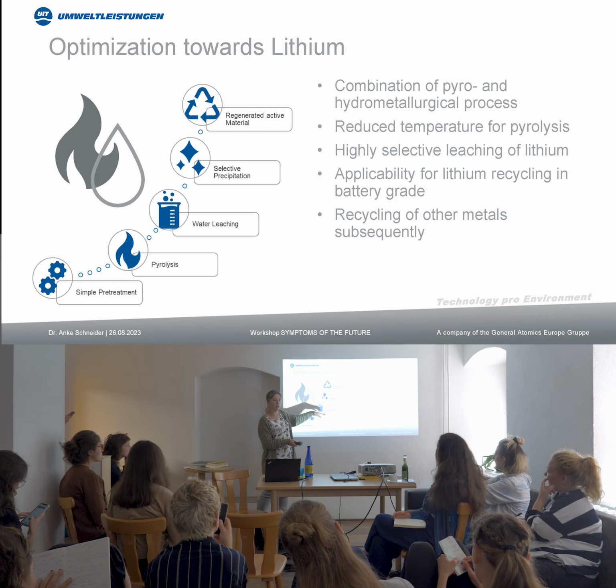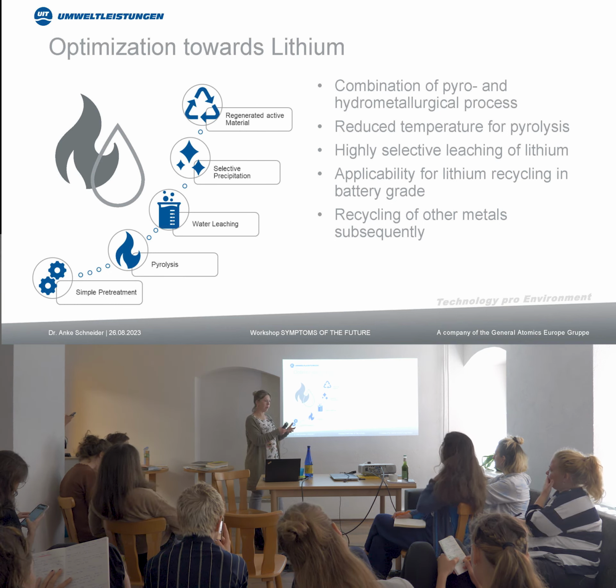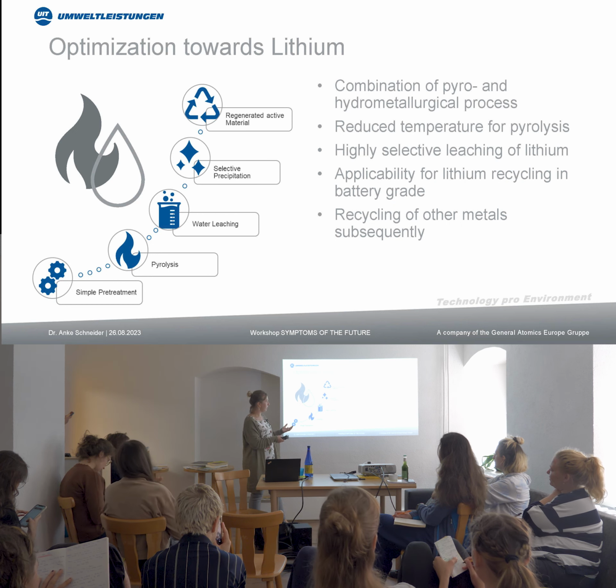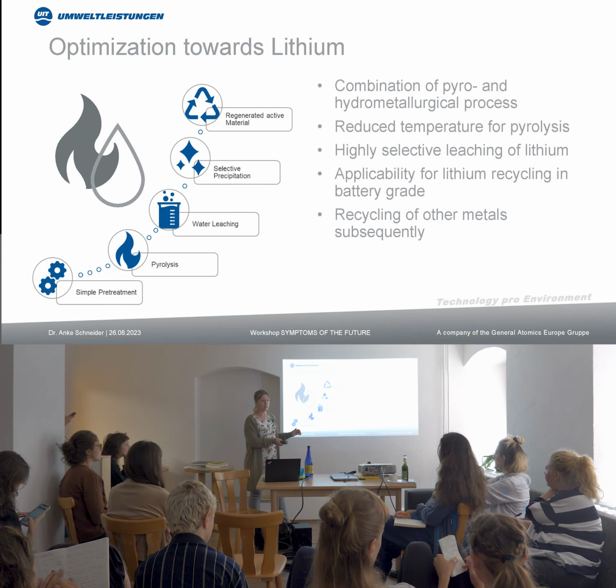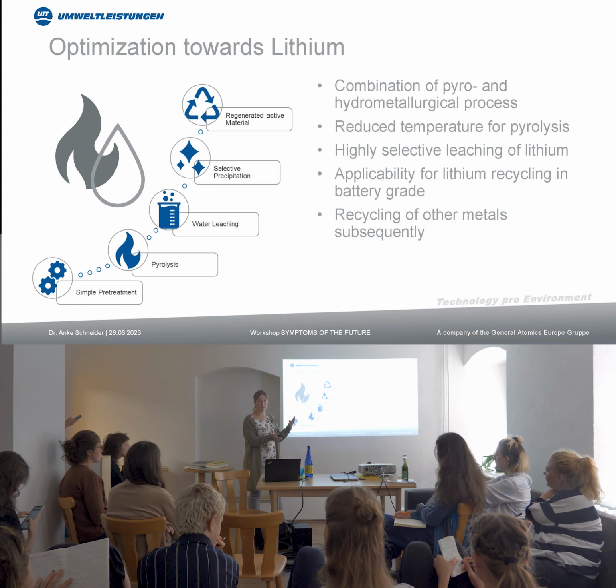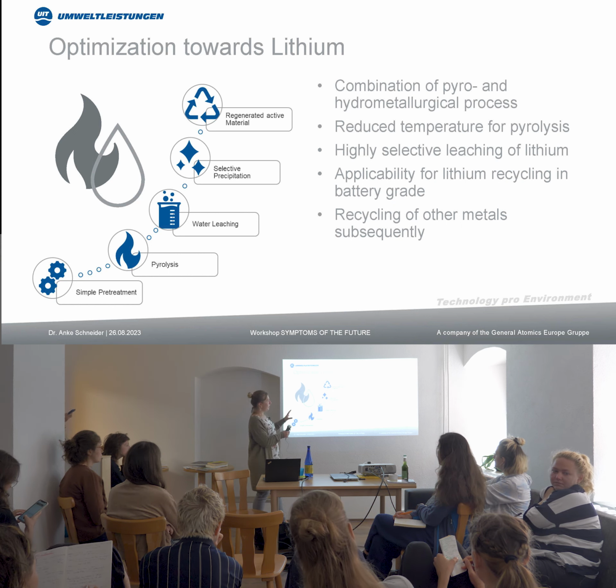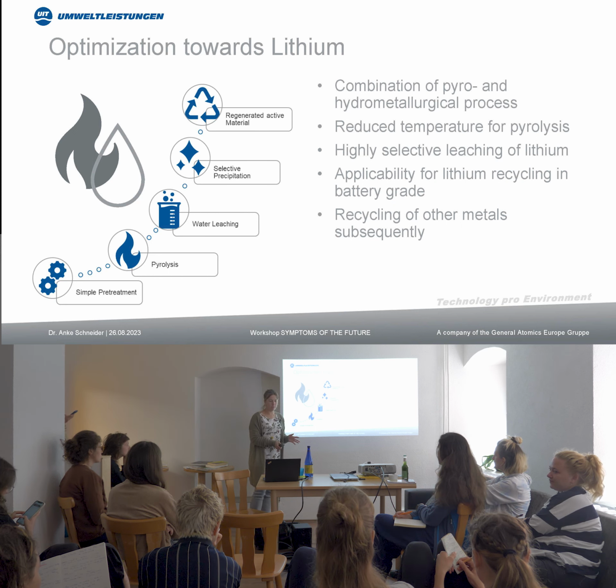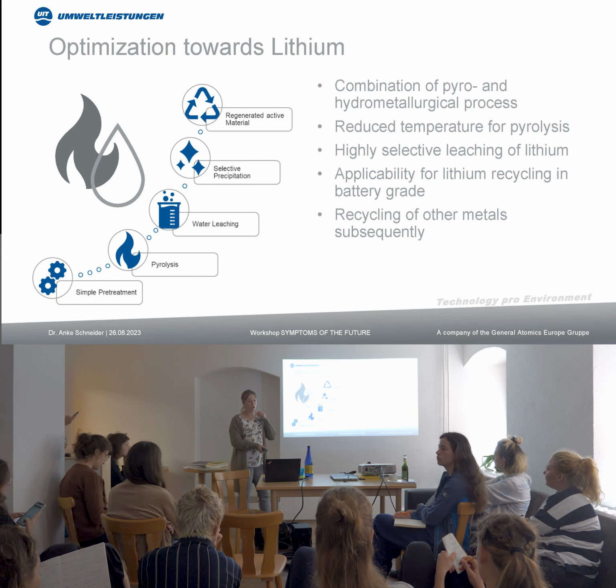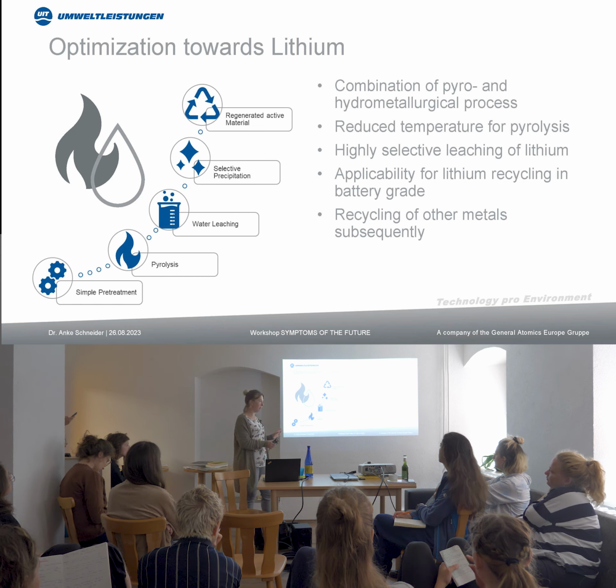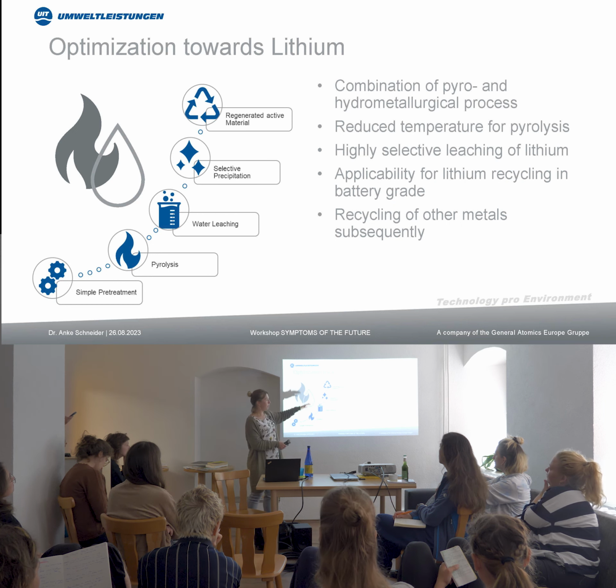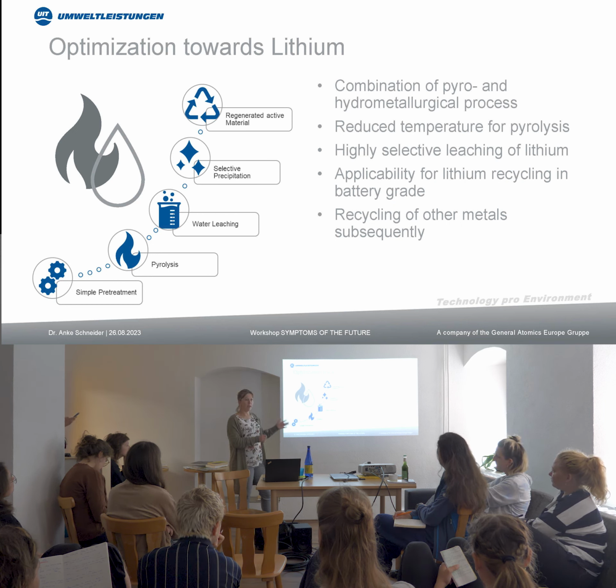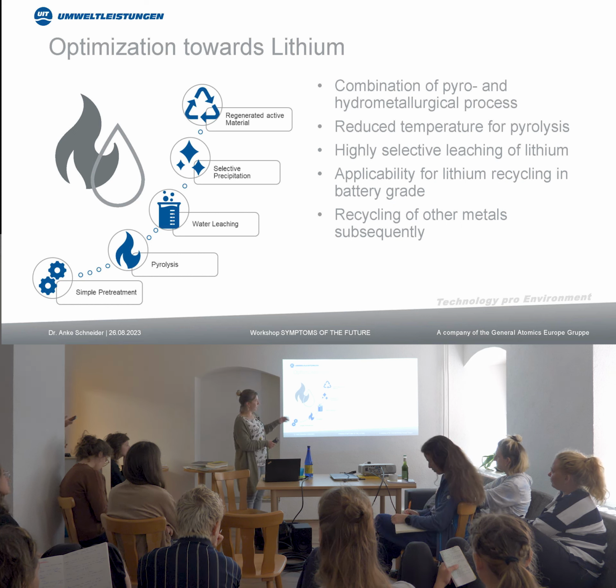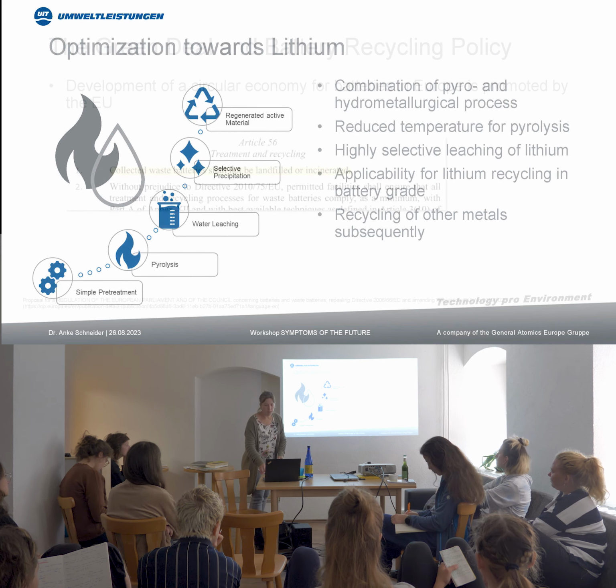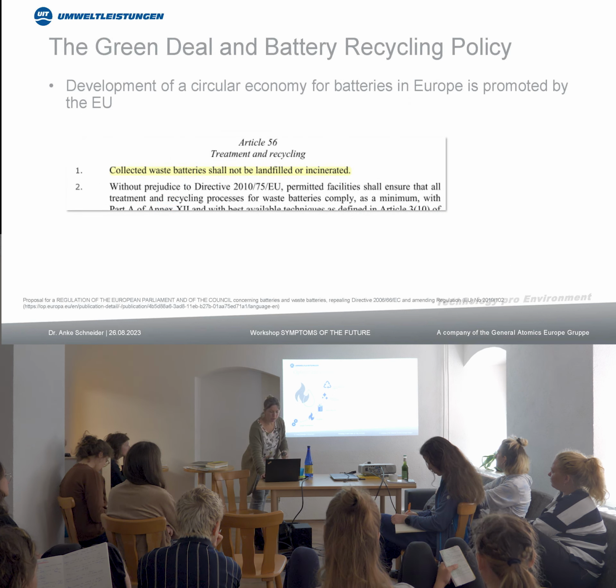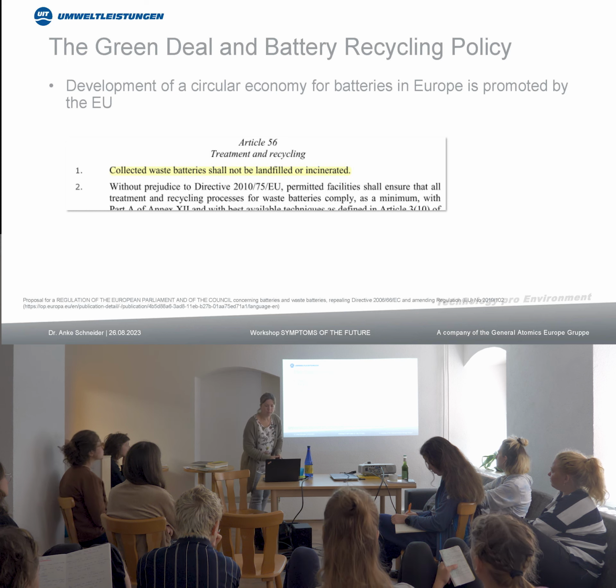And after this water leaching, you have your black mass. It's called black mass, the powders which are composed of battery material, which can also be recycled in a different stream. So for cobalt, manganese, nickel, and so on. So this is actually what is done now, what is the actual research at the moment, and also the projects I'm working in apply more or less this stream. Of course, you have some optimization potential in every step, and every company is doing it a little bit differently, but it's showing that.